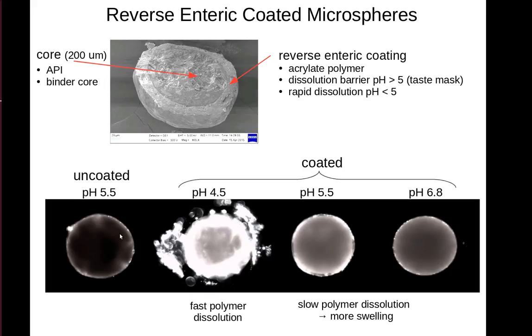Below is a snapshot of the dissolution of the microsphere and coated microspheres at different pHs. At a pH of 5.5, the uncoated microsphere dissolves over approximately 15 minutes. At 4.5, there's very rapid dissolution. At a pH of 6.8, the mouth conditions, the polymer keeps the underlying formulation from dissolving very rapidly. And 5.5 is an intermediate.